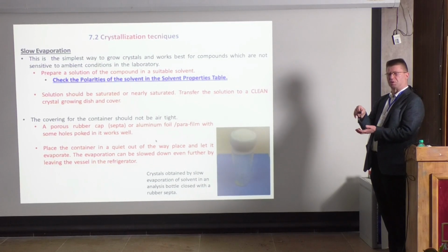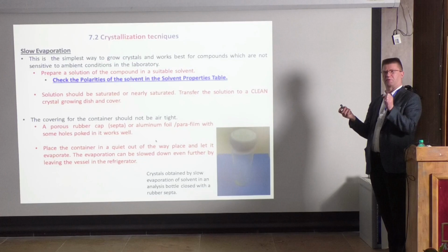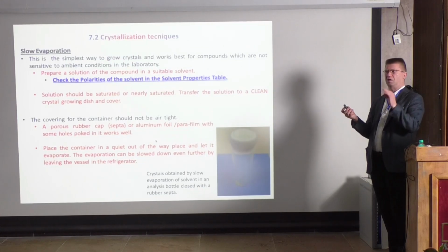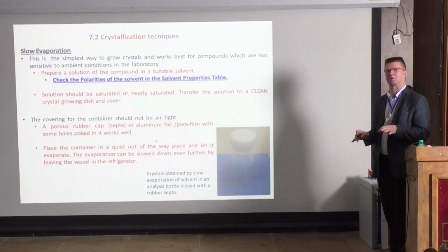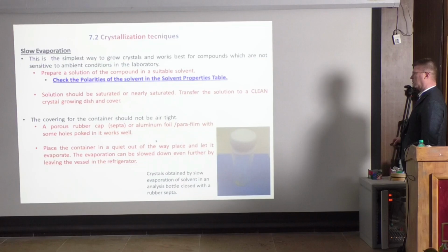But if it happens, then you should close the vessel and keep it, because then they are safe. Don't let it dry, because you don't know if the crystals contain solvent, and if they contain solvent and they dry, they die. So that's also a practical thing to do. So the idea is: keep it.